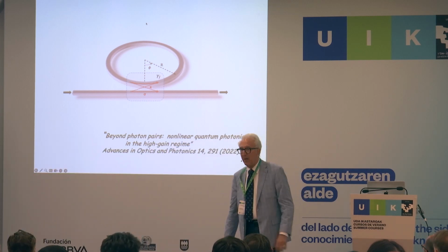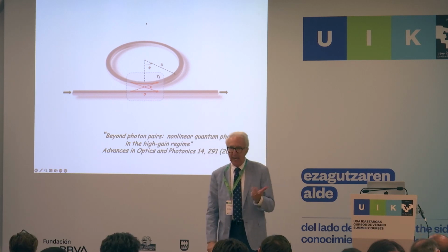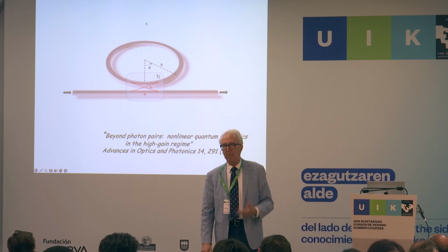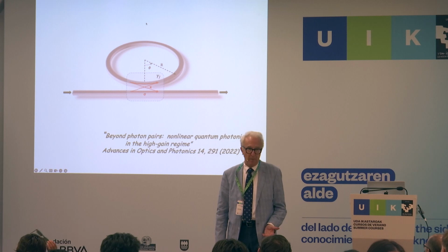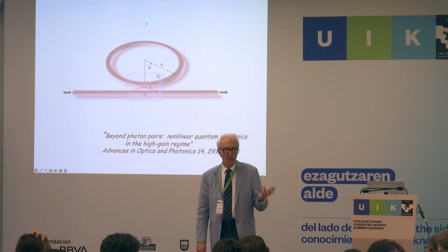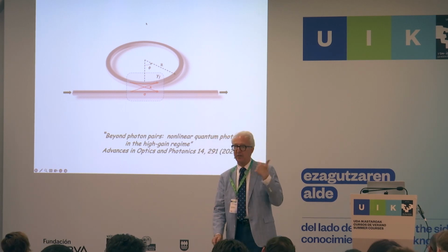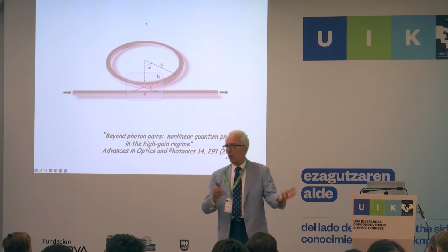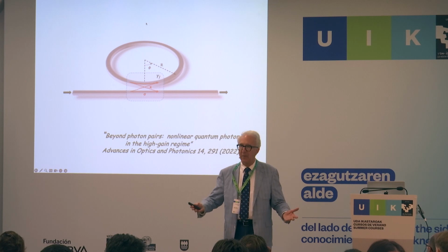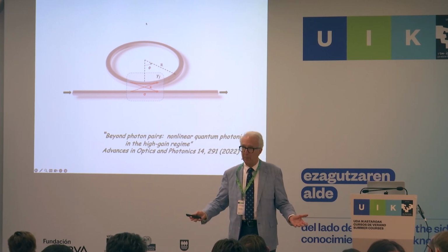Silicon nitride. First of all, it's an insulator at telecom wavelengths where you want to use your pump because you have all kinds of technology ready. Okay, so one wants to work at 1.5 microns for your pump. And it's a chi-3 process, so they're also generating photons in the neighborhood of 1.5 microns, a little bit larger, a little bit smaller. So you want something where you can work very well in the telecom. So you want it to be transparent at 1.5 microns.